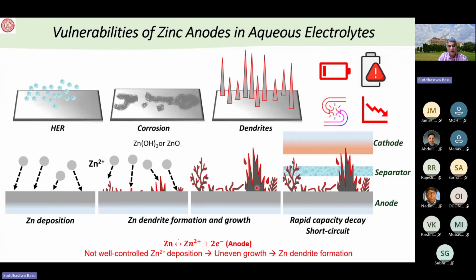The zinc deposition takes place like a dendrite, and then it perforates through the separator and reaches towards the cathode, and it's shorting it, which shows that it could have a very strong Young's modulus. This zinc dendrite has close to about 100 gigapascal of Young's modulus. So even if you have a separator made of a polymer or polypropylene, it pierces through it, reaches the cathode and touches it, making the cell die, through shorting of the anode and cathode by the zinc dendrite formation. So that is what you want to prohibit, and that is why the zinc aqueous battery life is very low.